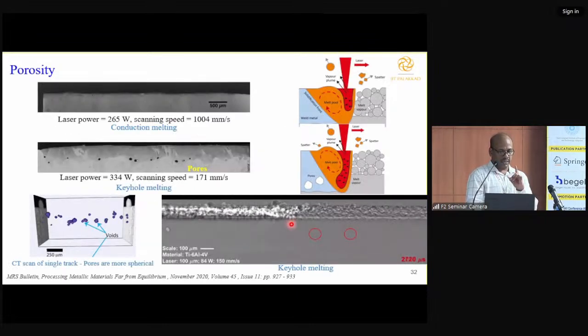The main reason for all these things is porosity. When you say porosity, you can see this video captured while doing the process. Something is leaving out here, a blue and white colored thing. Then you see it goes further. That means the laser goes over the powder and the molten metal also moves further. So these leave pores in the deposited material. See the depth, how much it is: around 200 micrometers down. If it goes like that, it will leave pores in the material, and getting a good product is then difficult.